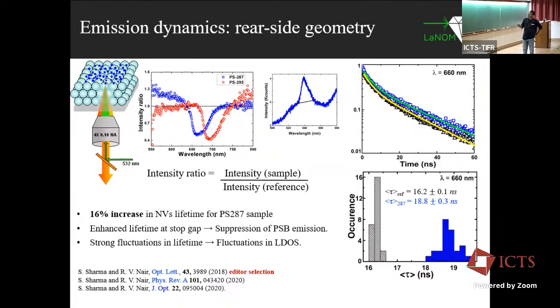And if you slightly increase the pump, you can see that the zero phonon line is a bit enhanced, but it is really a statistical thing. It may not work always. And as I said in the previous slide also, the lifetime does not show much change. Even though the intensity shows huge changes, the lifetime does not. Probably this is because these systems have quite a lot of disorder and also very low index contrast. But it still shows a system where you can really engineer the light emission from NV centers using these simpler photonic crystal structures.